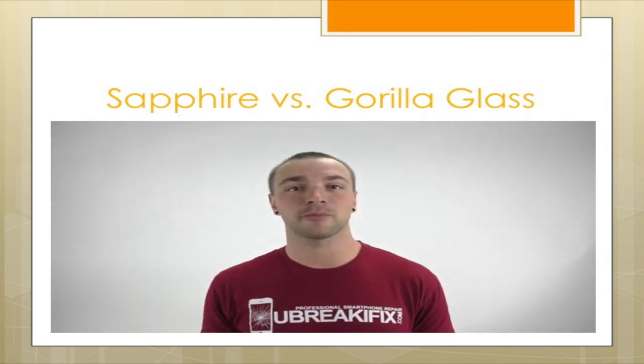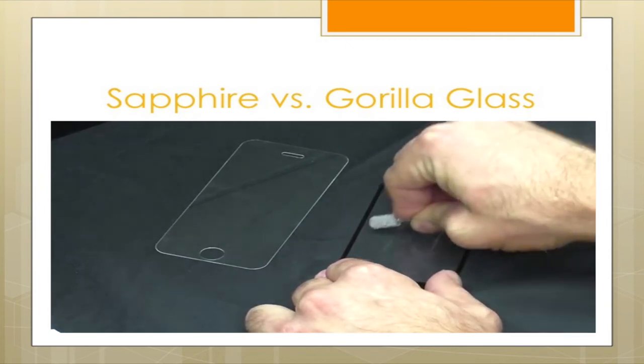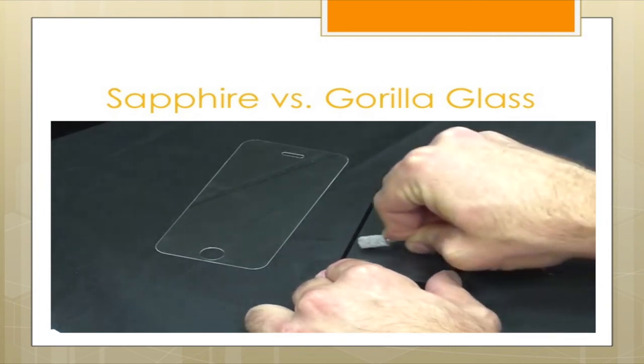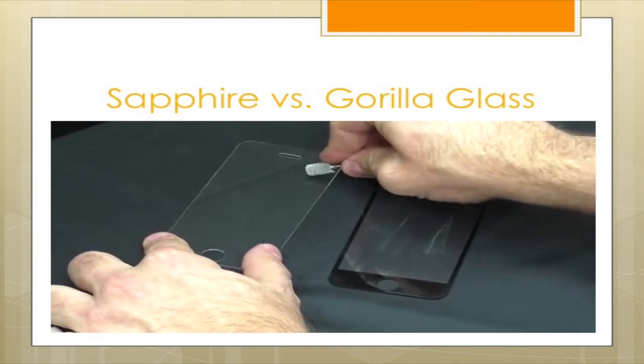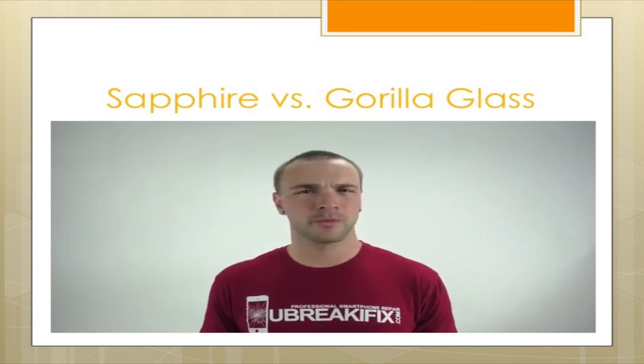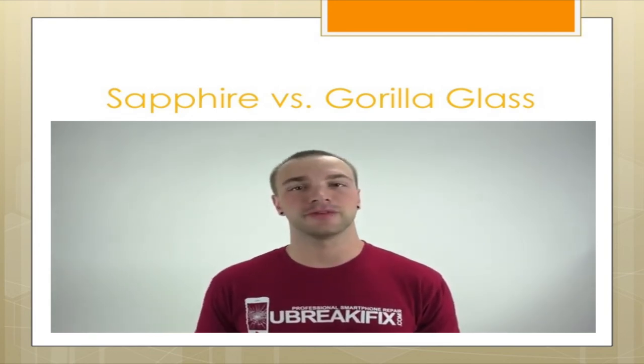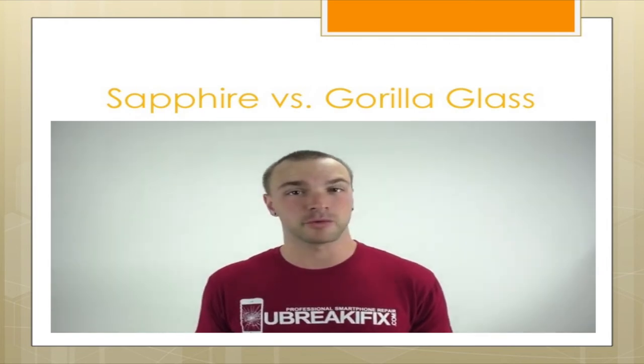Sapphire displays offer unprecedented scratch resistance. We scratch tested Gorilla Glass and Sapphire with a tungsten carbide bit, which is also a 9 on the hardness spectrum. The bit created huge gashes in the glass, but the Sapphire screen was completely unaffected. Sounds great. What about the downsides? Sapphire is very stiff, about 5 times stiffer than glass. So will it really lead to fewer broken screens?